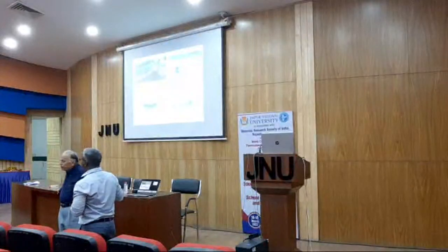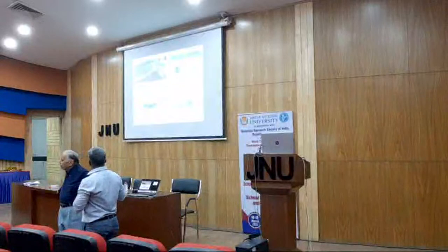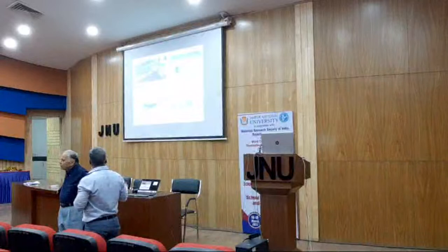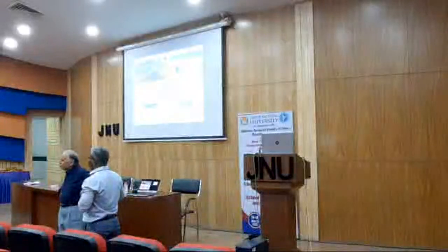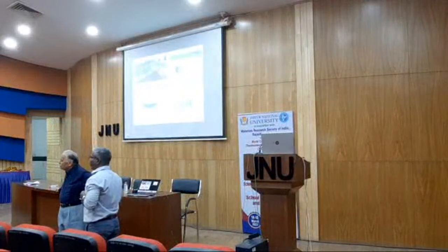I'll show you, sir. I'll finish this and come back. Here we can see the linear actuator. We measured the resistance at that point. Whenever we increase the time, the resistance should be constant. We want to know the device resistance whenever flexible stretch, elongation or compression happens, and over a number of cycles, how the resistance changes. We went for almost 1400 cycles, with each minute going for almost 7 to 8 cycles of bending and elongation. We did that, and we are doing a little modification to upgrade it. We started this recently, 6 months back.